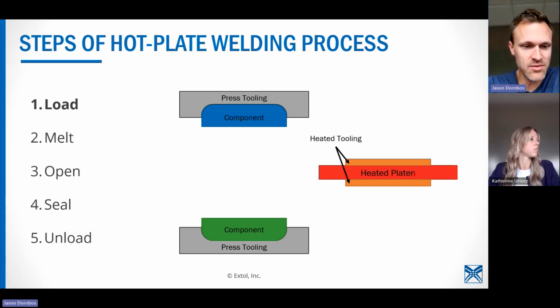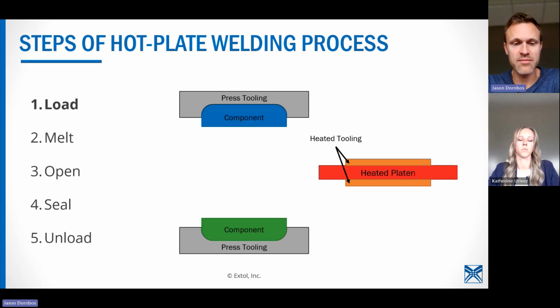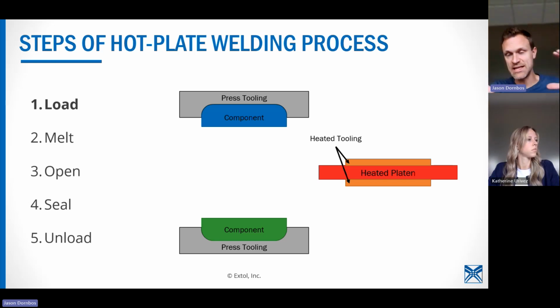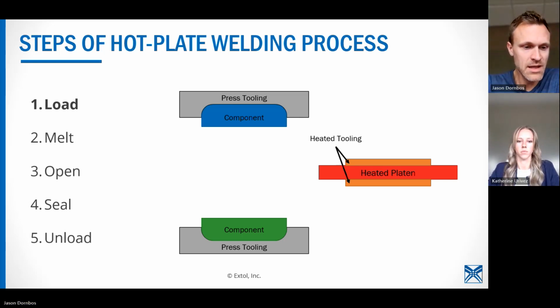The surfaces where we're actually going to be welding, if this was just a bottle or a small part that had a rib along the perimeter, there might be just weld ribs along the outer edges. Sometimes there's weld ribs on the inside components of the parts. The press tooling needs to support the part as close to those weld surfaces as possible so that they don't bend or deflect out of the way when force is applied.